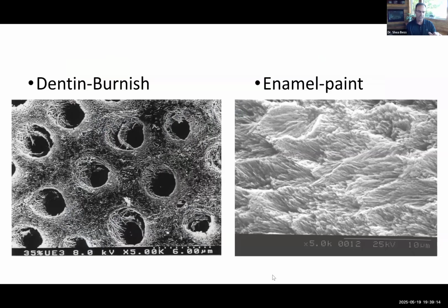When you look at this slide, here's an SEM of dentin. You can see all of those collagen fibrils. Think of them like little pieces of rebar. And when you're putting the adhesive on dentin, you want to burnish that adhesive in there. You want to really scrub and try to force that adhesive down into all of those collagen fibrils. When you're placing it on enamel, you don't want to burnish, you just want to paint.